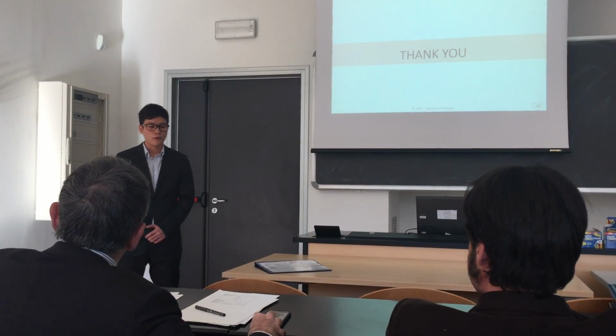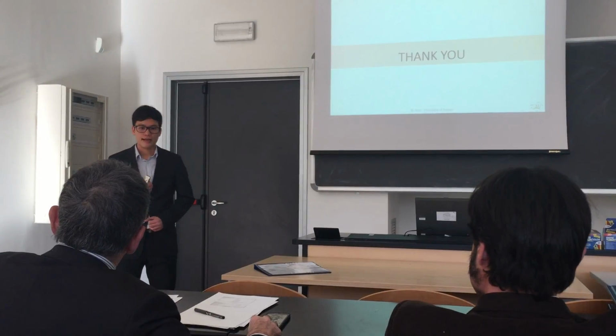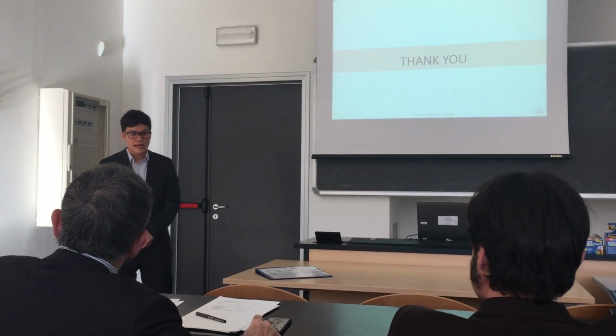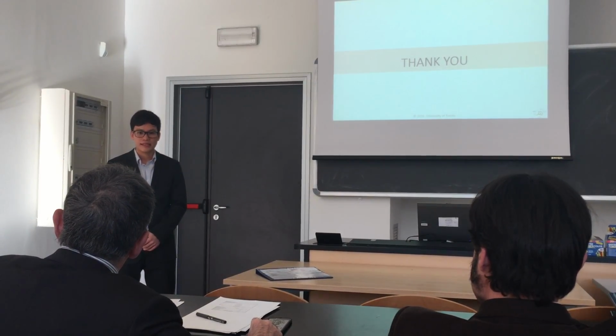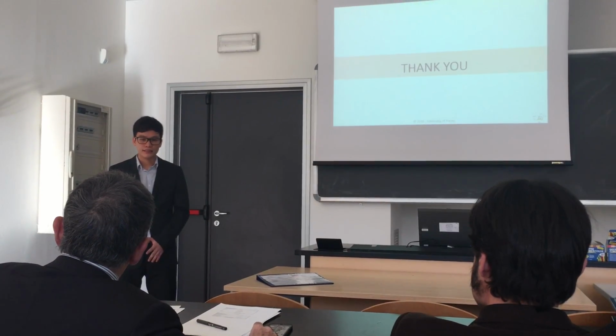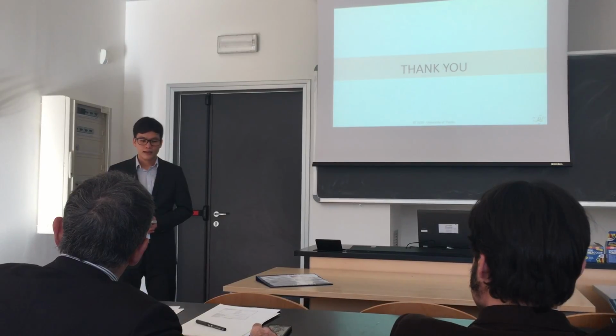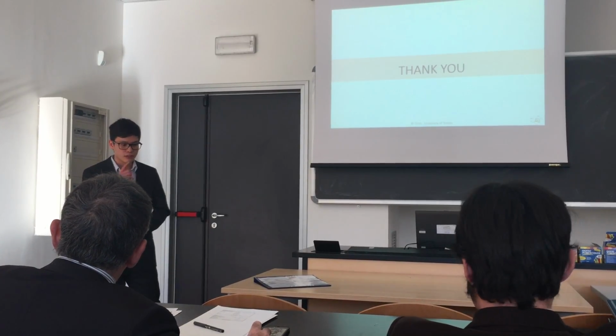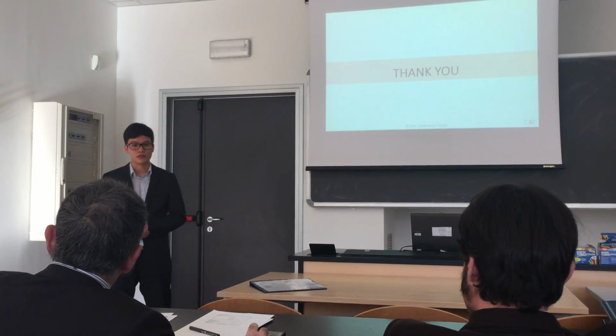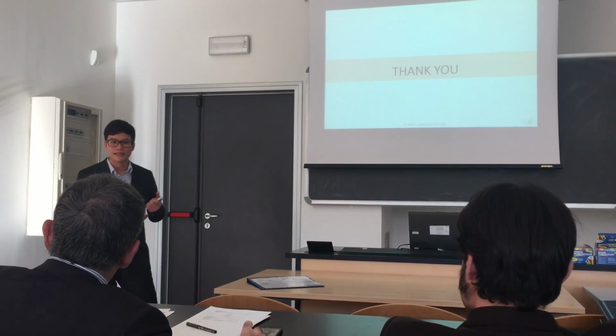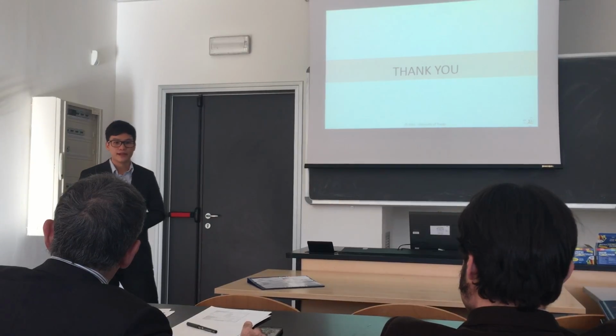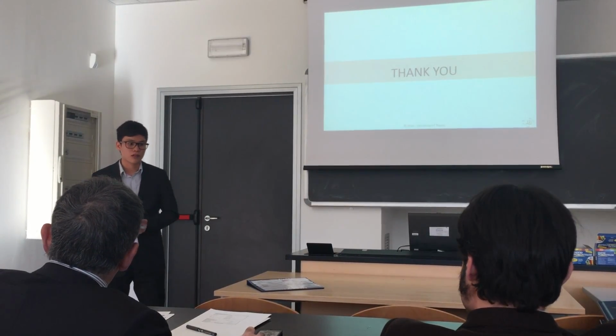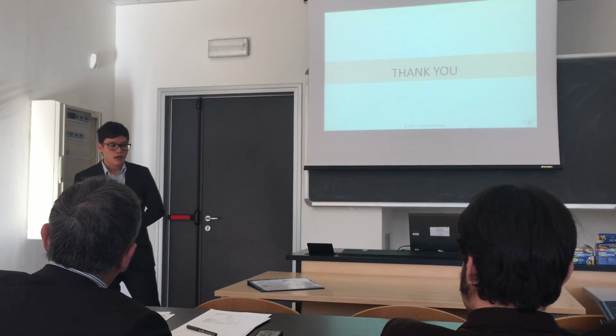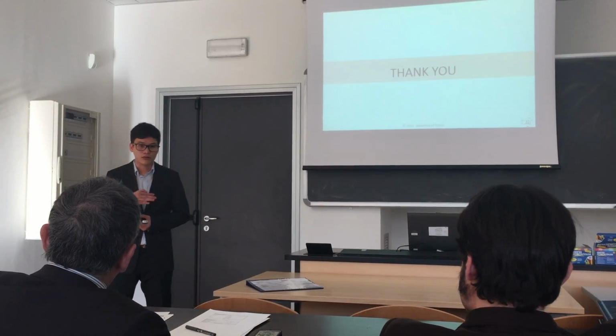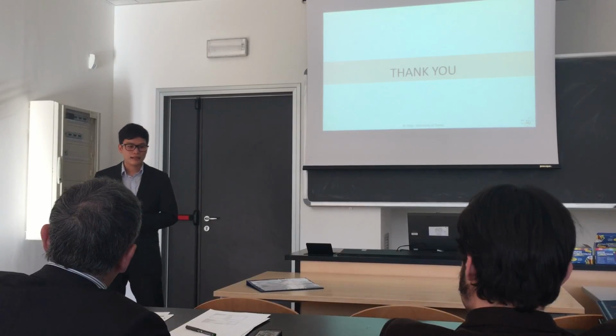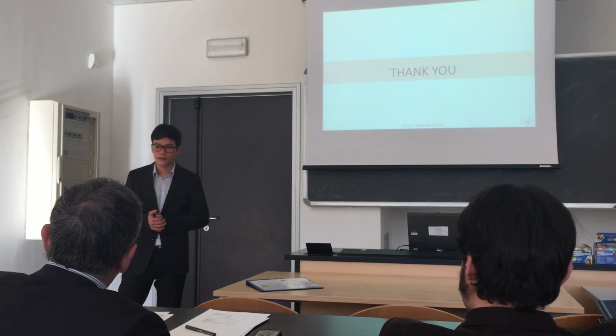Yes, it's an interesting question. According to my knowledge, I read many papers from the literature, and in some papers, with the introduction of the nanocellulose, they tend to decrease the water vapor permeability, and this is also an excellent property of the nanocellulose. The main point here is the nanoscale of the nanocellulose, because you can see that in the work by Bayer, he introduced microcellulose in the resin. However, it tends to absorb more water, due to the hydrophilicity. But when we integrate cellulose down to the nanoscale, it tends to have this behavior, and my results are also in good agreement with other literature.